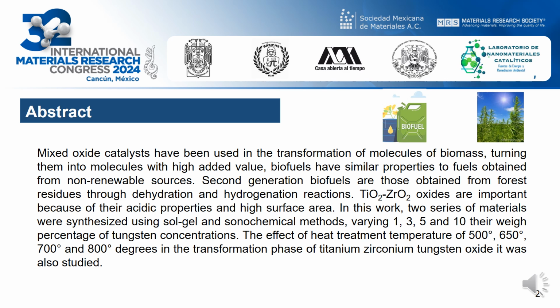In this work, two series of materials were synthesized using sol-gel and sonochemical methods, varying the weight percentage of tungsten concentration: 1, 3, 5, and 10. The effect of heat treatment temperatures of 500, 650, 700, and 800 degrees on the phase transformation of titanium zirconium tungsten oxide was also studied.